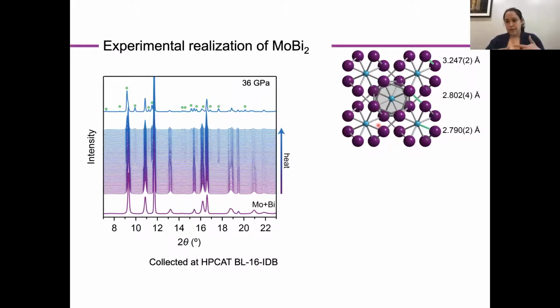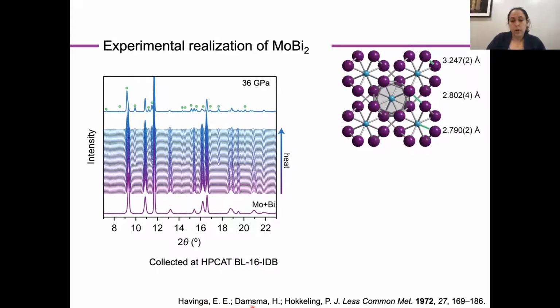Moreover, because this first molybdenum bismuth binary intermetallic forms in the copper dialuminide structure type, there's a lot of literature to draw on to contextualize these results. And so I'll direct your attention to a series of Havinga and coworker papers from the 1970s if you want more details. But in particular, it has been emphasized the importance of the heterobimetallic interactions in the structure type. And so I'm highlighting the shortest molybdenum bismuth distance here, comparing that to the radii of the metals at this pressure. You can see that this is quite a bit shorter, suggesting a significant and unique metal-metal bond.